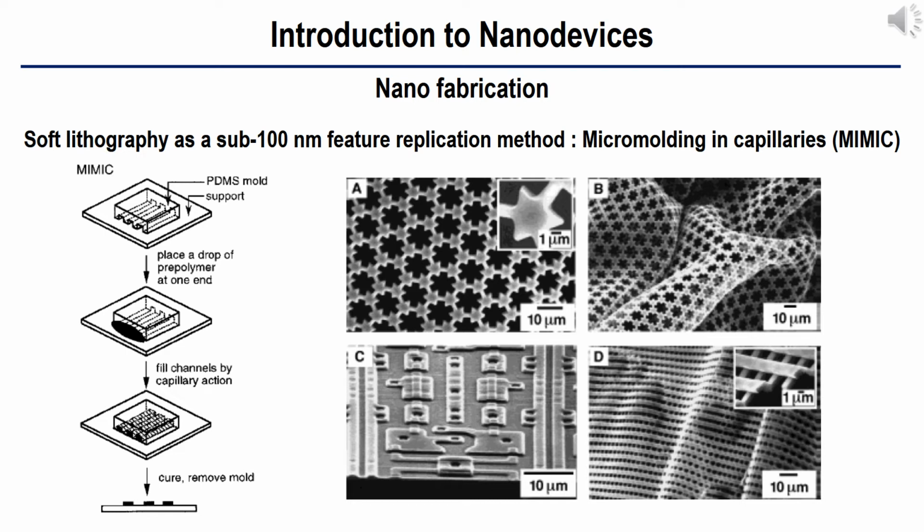There are several limitations in this method. Isolated structures cannot form a channel network. In addition, the rate of filling over a large distance decreases. Finally, the gas in the channel appears to escape by diffusing into the PDMS.